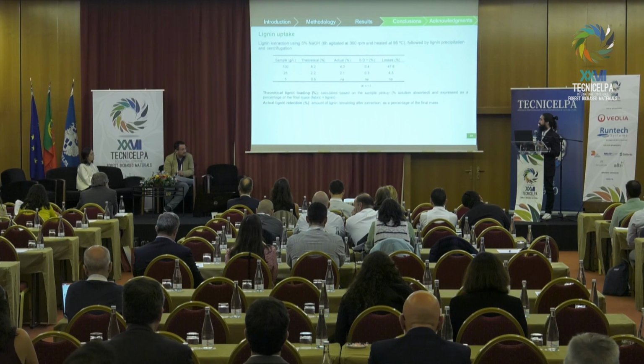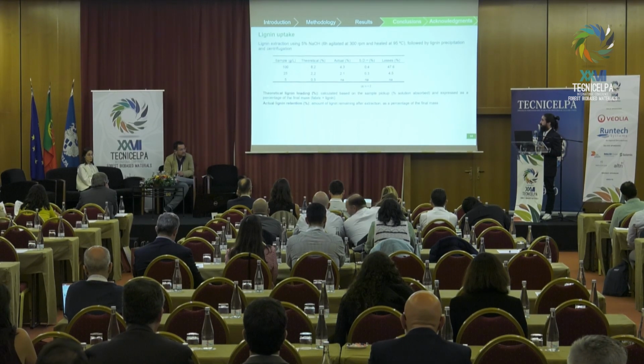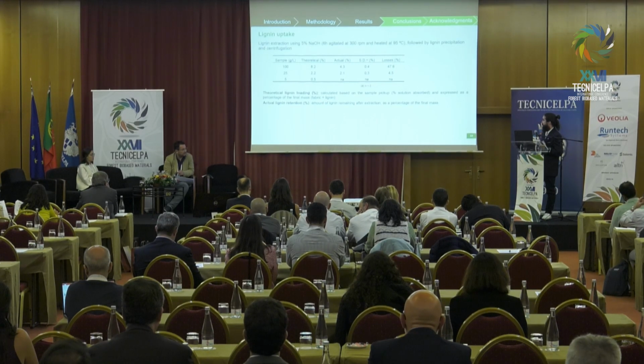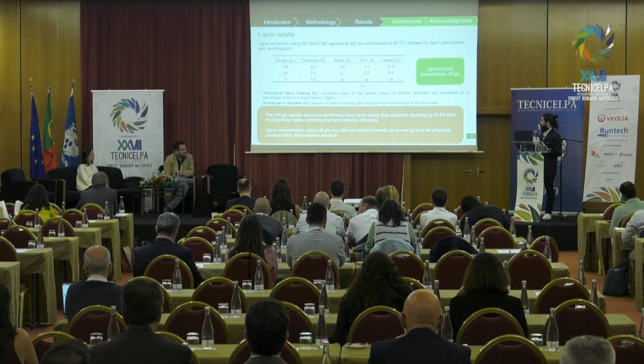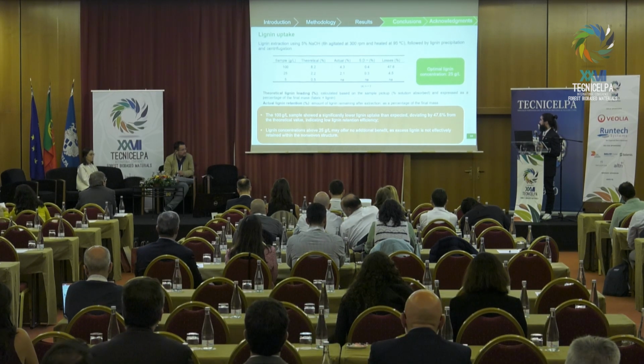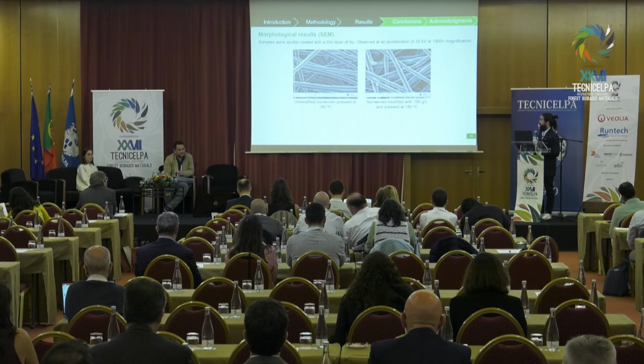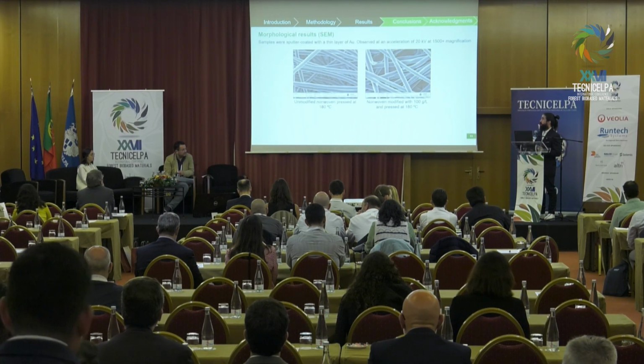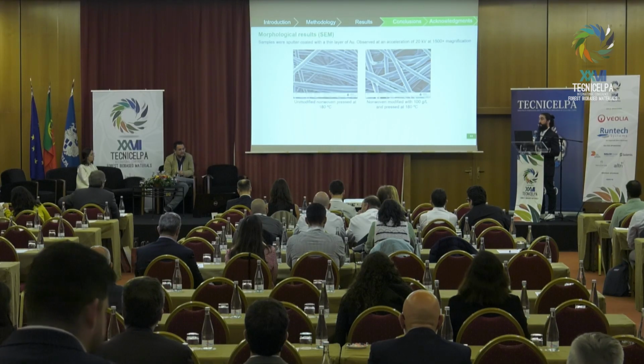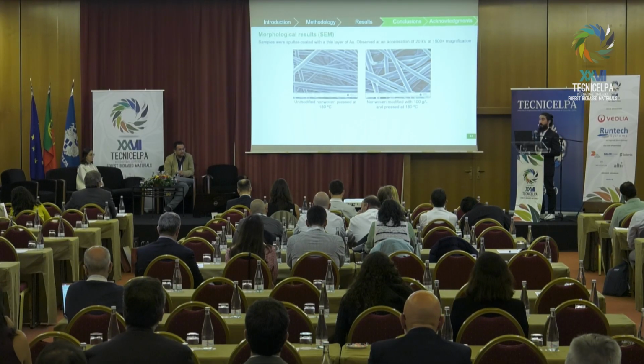So we believe this is the optimal point in our process. And with 5%, it was just such a small concentration that we didn't even measure. So according to these results, once again, the intermediate concentration seems to be the most appropriate one, the better in terms of properties. We also want to assess visually, not only visually, but with SEM imaging, how the lignin will be distributed in our nonwovens.